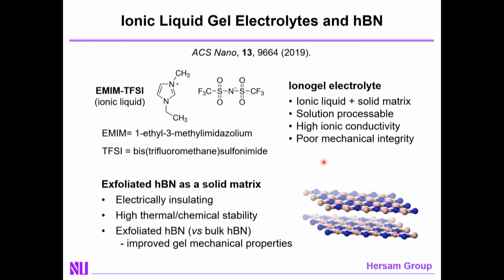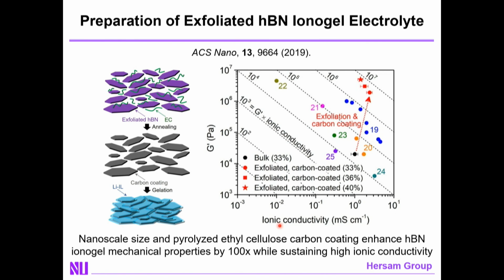So the way in which we're going to overcome that is to utilize another 2D material, in this case hexagonal boron nitride. We're going to blend it with ionic liquids to form a gel. The beauty of the hexagonal boron nitride is that it's electrically insulating, has exceptionally high thermal and chemical stability, and as you'll see in the next slide, allows us to get much improved mechanical properties compared to conventional ionogel electrolytes. The reason for this is twofold.